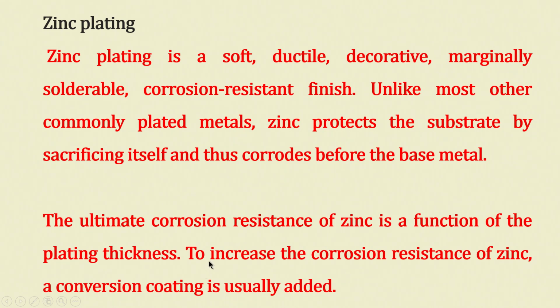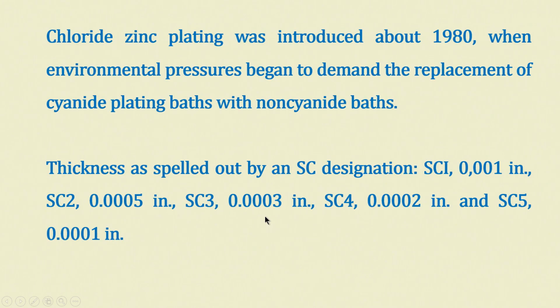To increase the corrosion resistance of zinc, a conversion coating is usually added. You have to look up the definitions of conversion coating for further information. Usually people used to coat zinc from a cyanide bath. Again, environmental considerations normally do not permit cyanide plating. So, nowadays there are processes which use zinc chloride as an electrolyte, introduced only since 1980. When the environmental pressure began to mount, replacement of cyanide became necessary in most countries, and non-cyanide baths have been developed over the last 20-30 years.